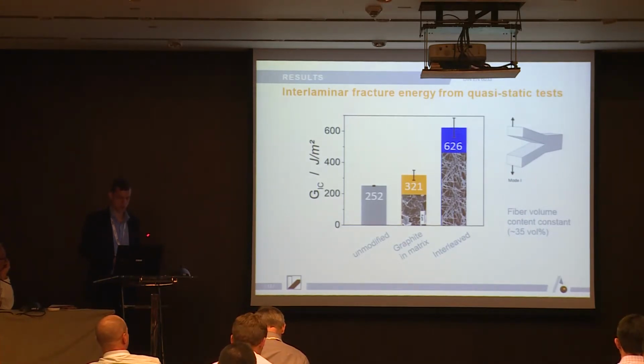First results, which I got from the static test. First I had my unmodified material, then one with the graphite matrix, and then the interleaved one. You can see that there is an increase in the fracture toughness of these materials. And as I said, this material is comparable by fiber volume content, to allow a comparison of these materials.